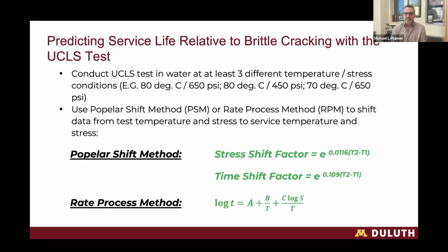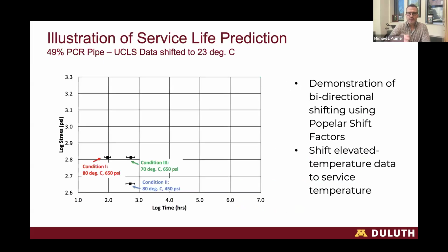We did that by conducting this test in elevated temperatures and elevated stresses, and then correlating that to service temperatures and service stresses. This is a very typical practice in the geosynthetics and plastics industry, where we can use the principles of Arrhenius to test at elevated temperature conditions and then extrapolate the data to service conditions that might be more appropriate for your given application. Two of the most common methods are called the Popelar Shift method and the rate process method. For the purposes of this presentation, I'll focus on the Popelar Shift and just show you how this is done.